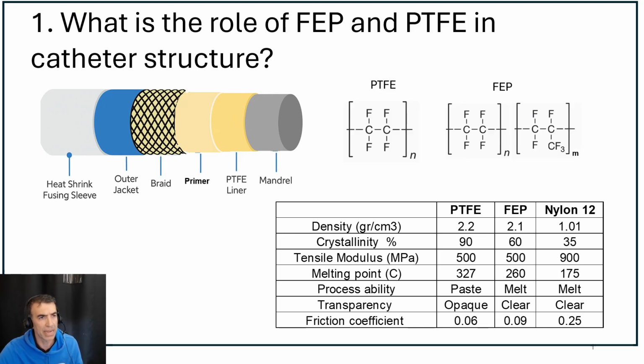After that, you need a braid. A braid is a crosshatch wire structure that can be made from stainless steel or nitinol, and it adds kink resistance and torqueability to the catheter, and significantly improves the flex modulus of the catheter. After the braid, you need an outer jacket. The outer jacket is usually made of a material like Pebax, nylon, or polyurethane. When the structure is heated up, this outer jacket can melt, diffuse into the braid, and react with the primer, making the whole structure one.